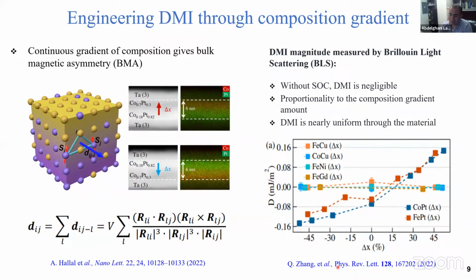For example, our collaborator used BLS to measure DMI strengths using Brillouin light scattering by looking at the asymmetry between Stokes and anti-Stokes peaks. So one can know the amplitude of the DMI. So the conclusion of this work: without spin-orbit coupling, DMI is almost zero. That means DMI is related to this bulk magnetic asymmetry as well as spin-orbit coupling.